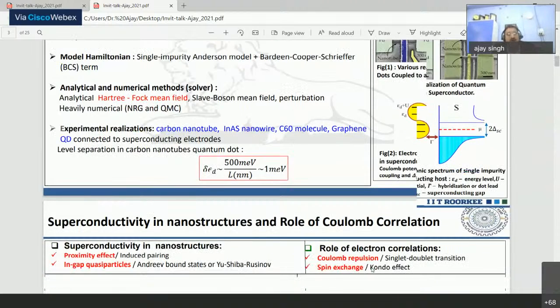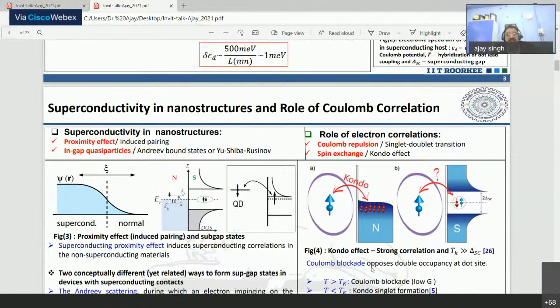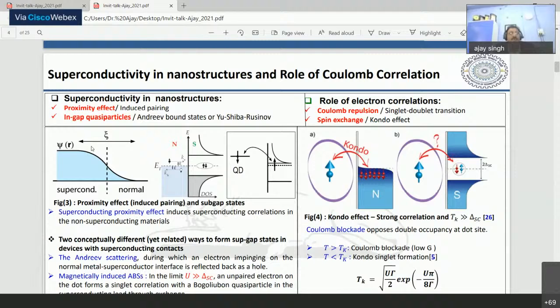If I summarize what we have to look for, we want to see superconductivity in a hybrid nanostructure, where two effects initially dominate. One is induced pairing, which is a proximity effect because of the significantly large coherence length. And then there is a possibility and a clear-cut experimental indication of Shiba-Rusinov states. These are the bound states which can carry current, and still the system is coherent.